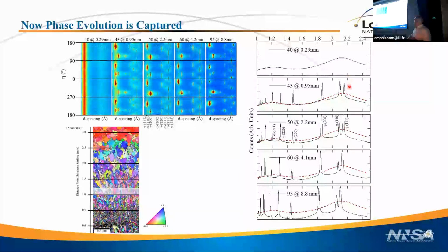And the liquid-solid comes as you see this broad peak disappearing with time. In other words, as you get further away from the melt pool. And again, it's really important that you have all of these diffraction peaks if you're to say something stronger than the alpha peak got smaller, right? I want to say the ferrite volume fraction got less, not the alpha peak got smaller.